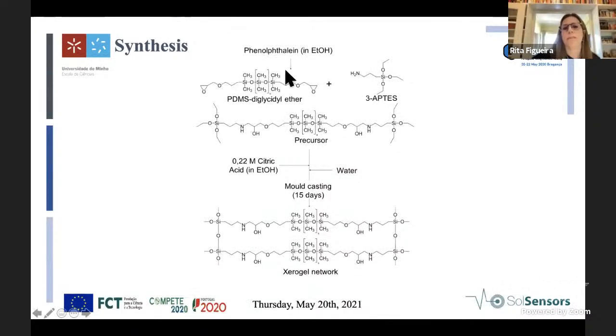The synthesis process that we used for this first approach is represented here. We made PDMS react with 3-APTES, and we obtained this precursor. We used as catalyst citric acid in ethanol and water, and we let it cure for 15 days in an oven at 40 degrees.